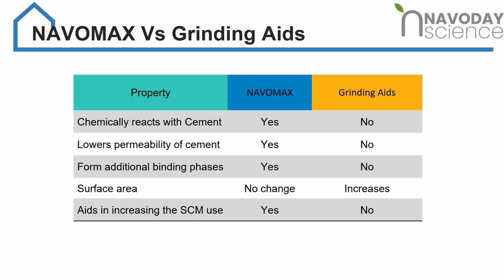So when you compare NAVOMAX to the conventional grinding aids, it chemically reacts with the cement, whereas the conventional grinding aids don't react with the cement. What the conventional grinding aid does is increase the specific surface area of your cement, thereby increasing the initial rate of the reaction. Whereas NAVOMAX chemically reacts with the cement to form additional binding phases, lowers the permeability of the cement, doesn't affect the surface area, and aids in increasing SCM use. Next slide, ma'am.